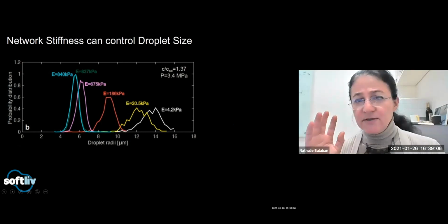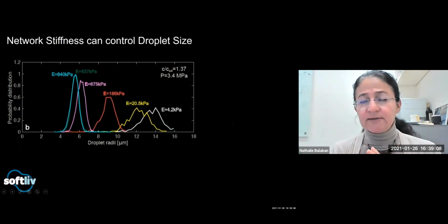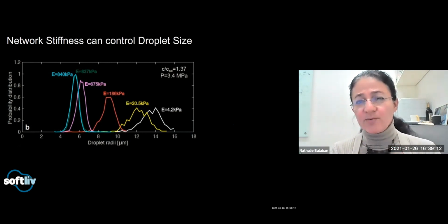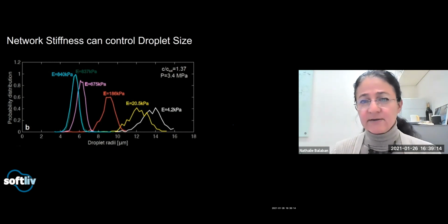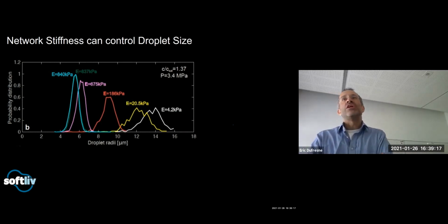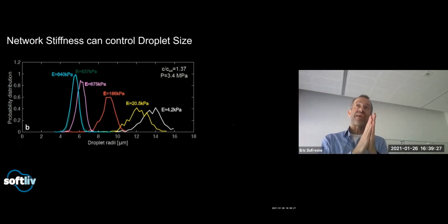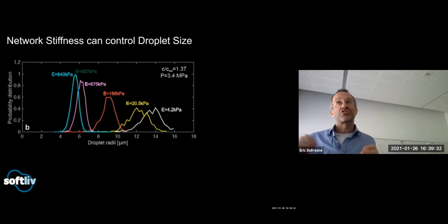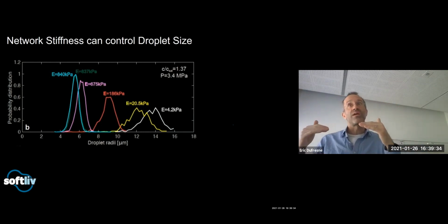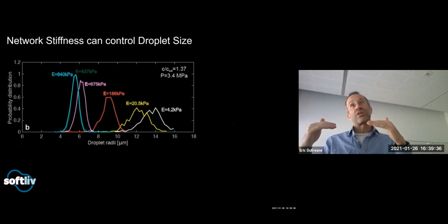So is the total volume of the droplet the same? Because it seems in the picture that you show that there are more droplets when they are tiny. Excellent, Natalie. Good point. So to the best of our ability, you know, we're doing light microscopy, the total volume of the liquid phase that we make when we cool is unchanged when we quench by the same temperature difference.